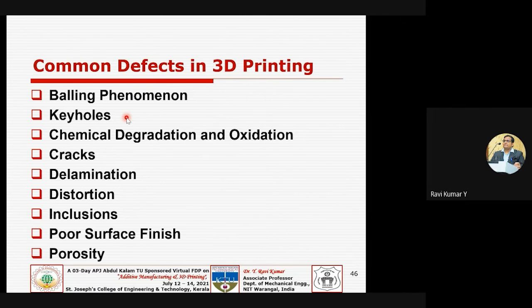And sometimes your material gets degraded. Chemically it can be degraded, especially if you take polymers, or even powder also. It can be, of course, oxidation. That is the biggest issue. Though you will be inerting it, and doing everything in an inert environment, typically using nitrogen or argon gas, still oxidation is the major culprit. And you do find some cracks inside your 3D printed structures, and delamination.